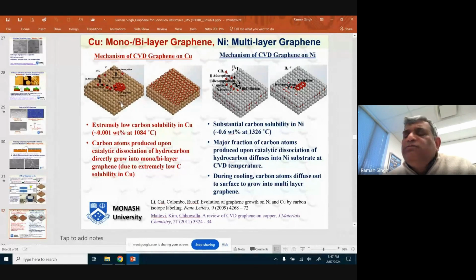Copper has almost nil solubility of carbon. So whatever carbon is produced because of splitting hydrocarbon, if you have maintained the right partial pressure, it will just reorganize itself as graphene on the copper surface. Whereas nickel has huge solubility of carbon, 0.68%, which is much higher. So the carbon that you produce will be diffusing into nickel, it will saturate it, and when you cool down, the solubility decreases with decreasing temperature, and carbon will be diffusing out, and it will organize itself as graphene.